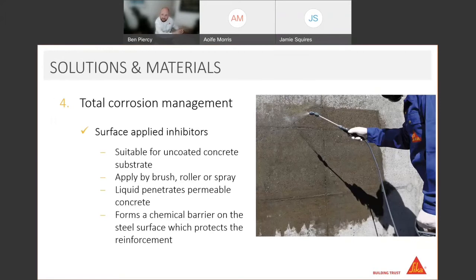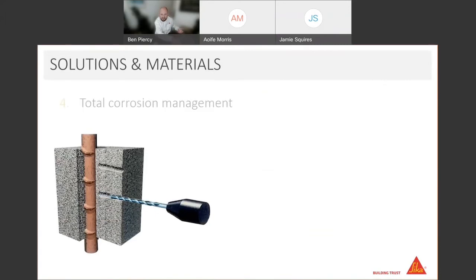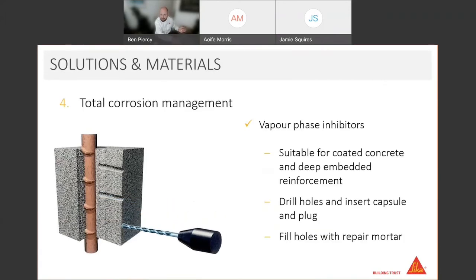The first up we're going to look at is natural carbonation. If the concrete's carbonated, and also uncoated, we can use our migratory corrosion inhibitor, which you see there. It's not very labor intensive, quite easy to apply, and can be done by brush, roller or spray. The brand name of which is FerroGard. FerroGard penetrates through the concrete and migrates towards the rebar, forming a chemical barrier on that steel surface, which protects the reinforcement and doesn't allow the elements that you saw earlier to pass through.